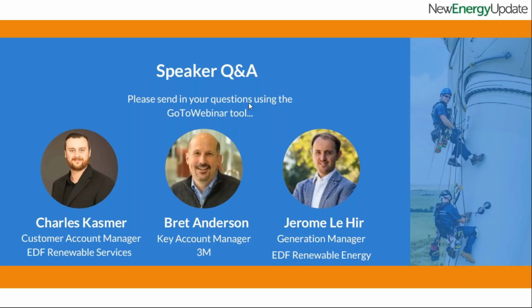Mm-hmm. Okay. This is Charles. I'd like to add one more thing. One of the reasons EDF has gone with the tape is that we have in the past used the coatings, and the coatings do have a very narrow weather tolerance. Also, when you're applying the coating, you have humidity and contamination risks. That coating is meant to be installed within very controlled environments. With the tape, we can install it within a wide range of temperature and humidity ranges, and it's a very quick installation. Our techs can install it within 45 minutes once the surface is prepped.